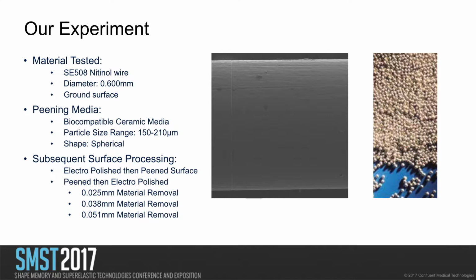One thing to note, I mentioned that the media is biocompatible, but even if the media itself is biocompatible, if a piece of that media gets lodged in the nitinol surface and can later come off inside the body, that can create issues with biocompatibility. So even though the chemical that the media is made of is non-reactive, we consider any media present to be non-biocompatible. And after this, we subsequently surface processed these wires once they had been peened in multiple different states.